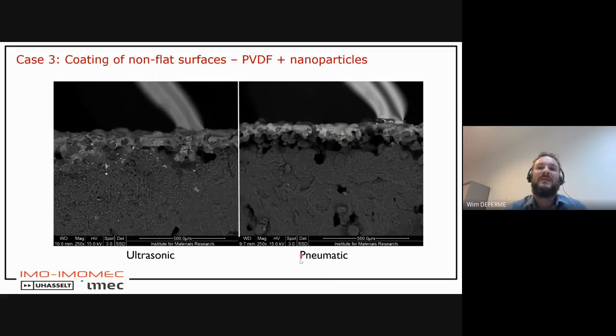Here you see the pneumatic spray coating, industrial spray coating. Here you see ultrasonic spray coating. And what is obvious is that the PVDF, the polymer, infringes more into the substrate, in the porous surface of the 3D printed part, than the pressurized one. And that's normal for the simple reason that here the droplets that you fire towards the substrate have a very low kinetic energy, while with pressurized spray coating, the speed of the droplets is much higher. And that means that they will not penetrate inside the first few micrometers of your 3D printed part, but will stick on top.